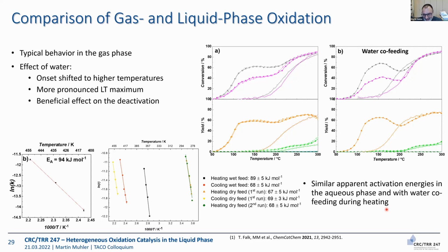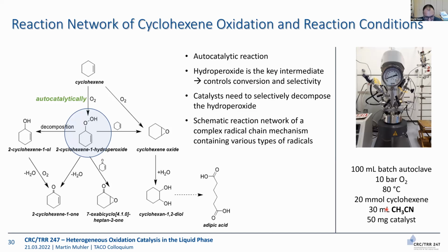So this is now the question, is the active site still the same when it's in liquid water? And of course, what you have immediately in mind is, it must be hydroxylated. And indeed, we saw the chemical reactivity of the catalyst is much lower. And there are ongoing molecular dynamics calculations that look at hydroxylation. OH minus is then much less basic than the oxygen anion, the O2 minus. So that means it's less likely that we form the propoxide, and it's then also the question, is it simultaneous bond breaking or first OH, then CH? That is still ongoing research. And we use this wet feed as an intermediate step between gas phase and liquid phase.